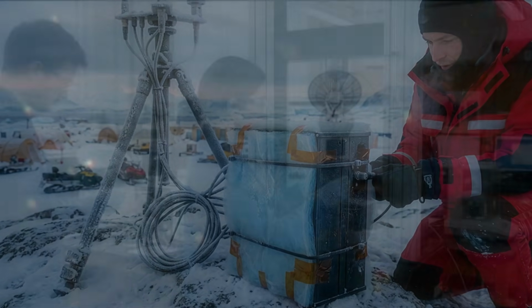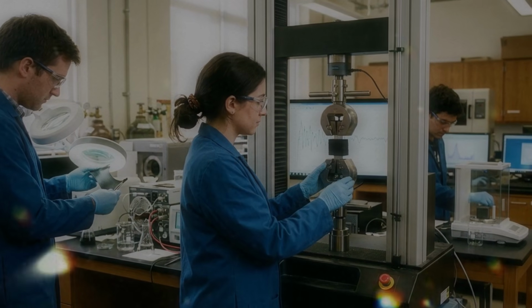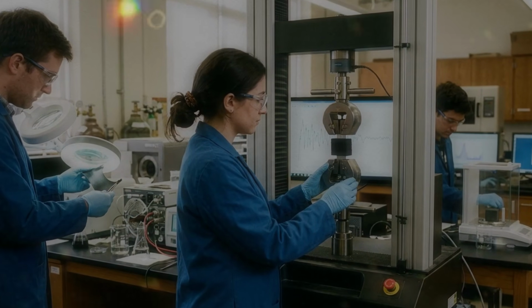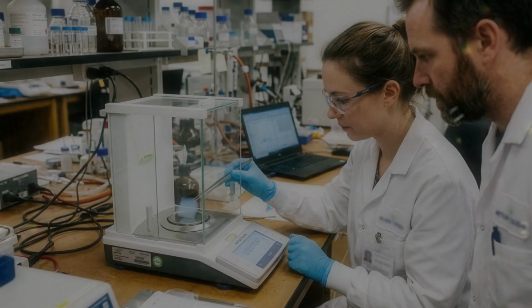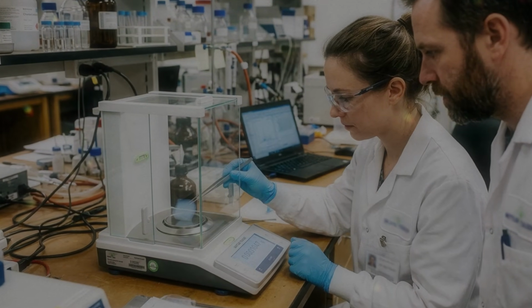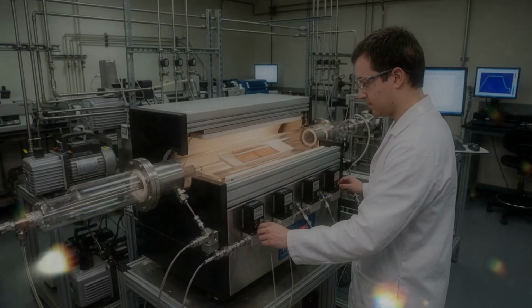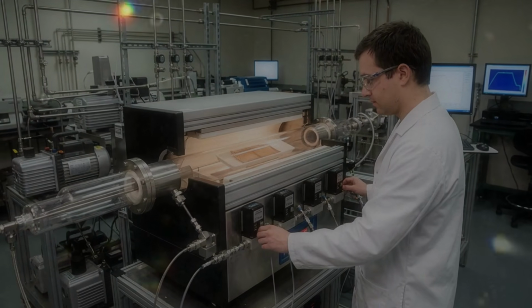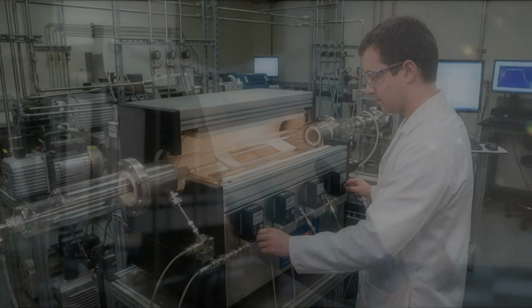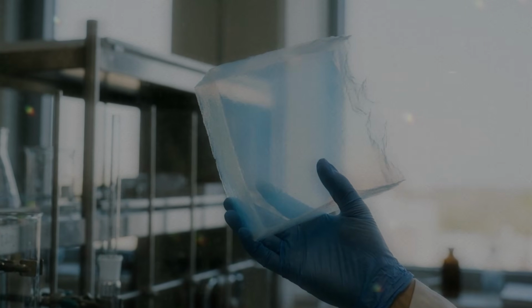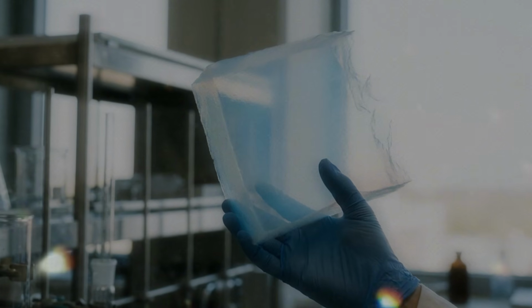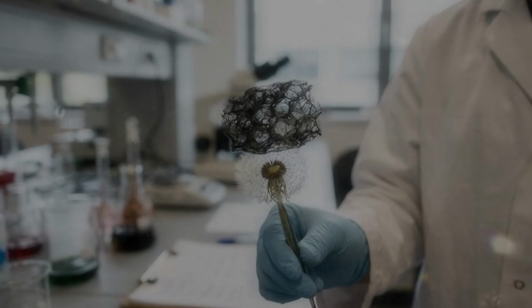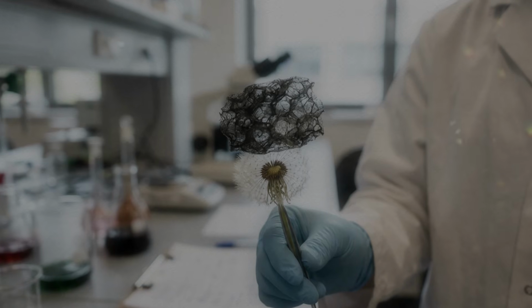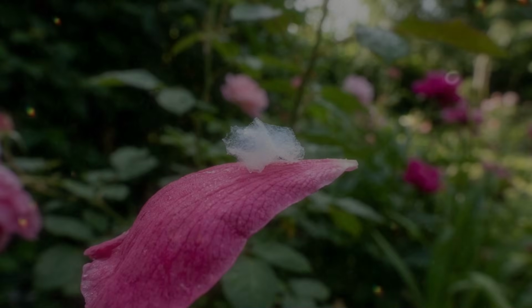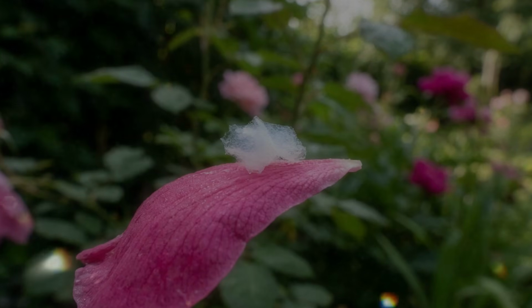This comparison sounds almost magical until the starting weight is remembered. A sponge that weighs very little does not need a huge amount of oil to exceed its own mass many times. The more important questions are how quickly it absorbs, whether it selects oil over water, and whether it can be collected and reused. A resilient graphene aerogel can be squeezed to remove part of the oil. It may then expand and absorb again. Other recovery methods use heating, pumping, or solvents. Each method has costs. Squeezing requires equipment. Heating requires energy and may release vapors. Solvents create another liquid that must be handled.